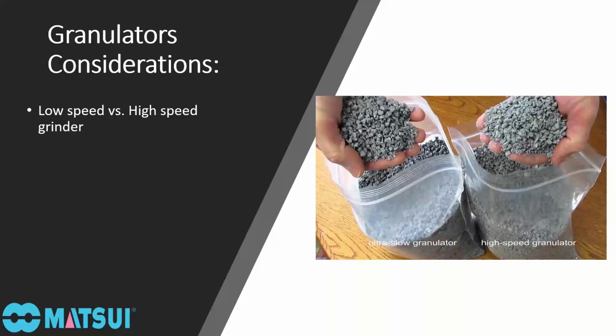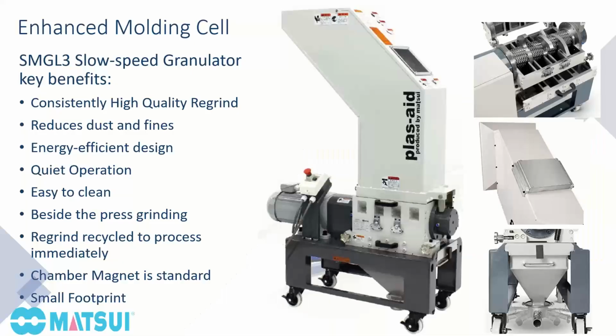Some concerns with high-speed grinders is they grind the material at a high rate of speed. And when this is done, a lot of dust and fines are generated. Also, there's a lot of miscut shaped material for the regrind. The regrind's not in a consistent uniform shape. There's a lot of miscut pieces. So then this regrind material would be taken back to the injection machine to be reused, put in gaylords or material tanks.